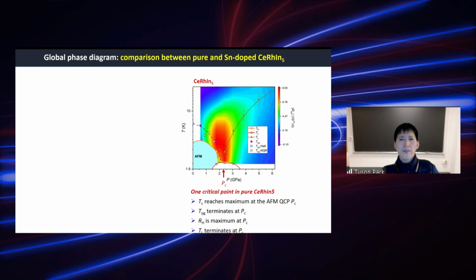Okay, so this is the contour plot of the Hall resistance in the temperature and pressure plane. Then you can see that the maximum in the Hall resistivity occurs near the AFM QCP point, and then the pseudogap temperature, and also this new line that shows the local minimum also, at this critical point.